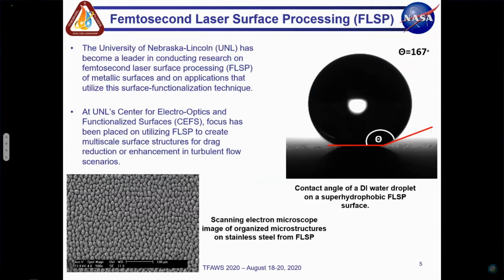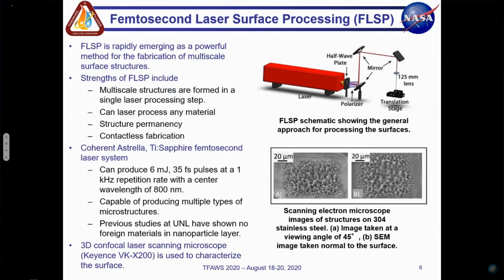Now, the multi-scale structures themselves you typically see with things like the lotus leaf and a lot of things in nature. Using these coatings, we're able to get superhydrophobic surfaces, as you can see on the far right, of these steel. It's a powerful method for fabricating multi-scale structures. One thing that's nice is that by processing with the laser, we get the multi-scale structures. As I talked about earlier, you're able to get microstructures, typically pillars, though we have gotten spheres before too. And we're able to get nanostructures on the surface, which make them ideal for both wicking with superhydrophilic surfaces and non-wetting superhydrophobic surfaces.